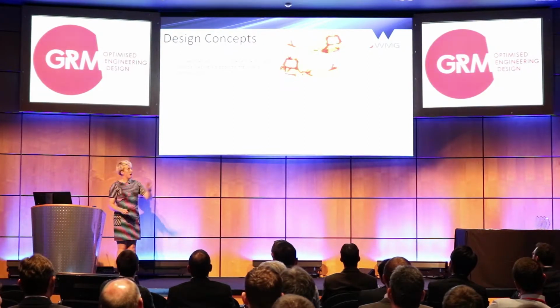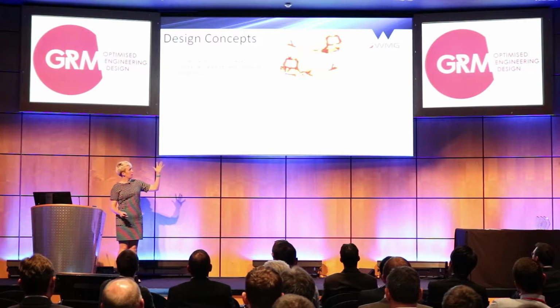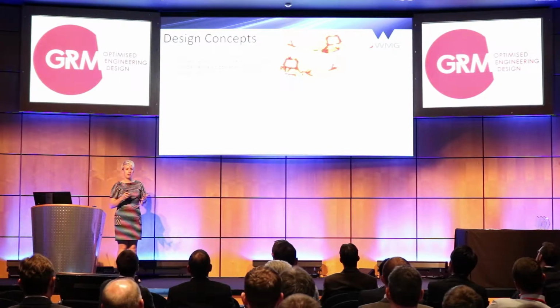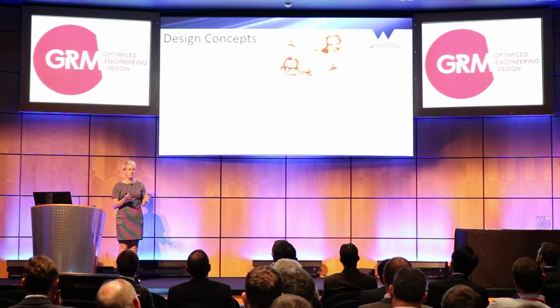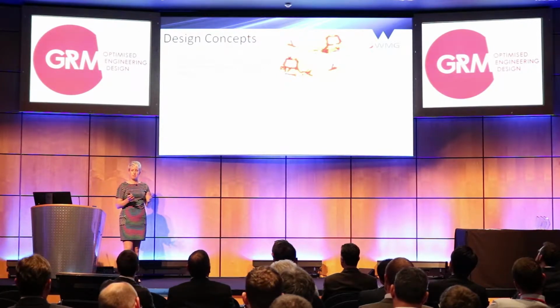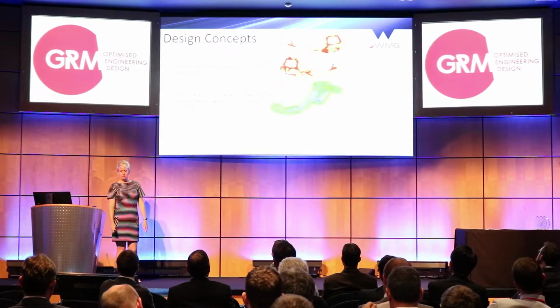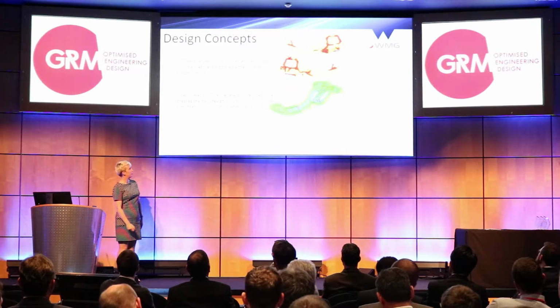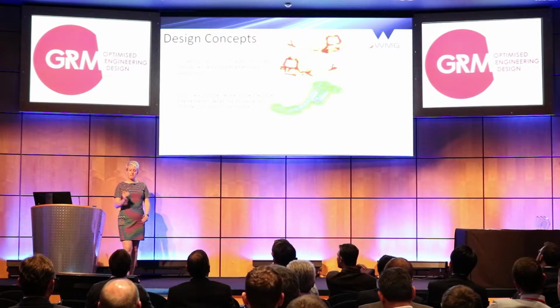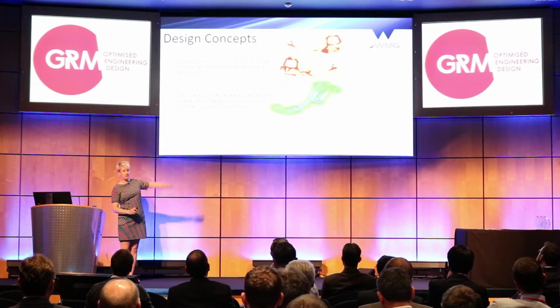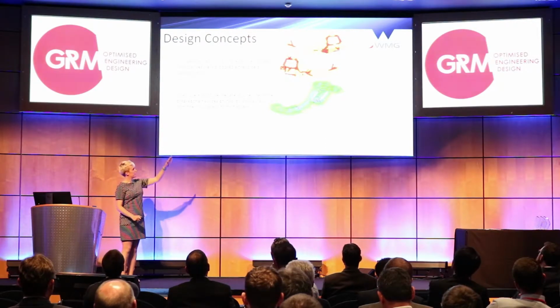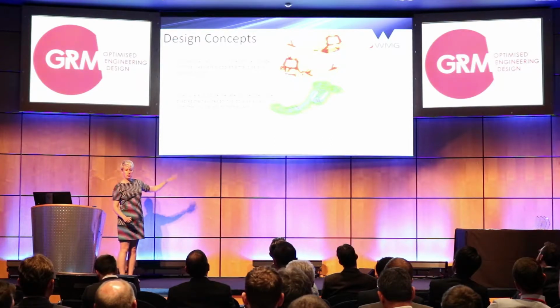However, this first design, that's like a rear and a forward of the part, had SMC on both sides. So when we add in the design for manufacture requirements, we can't achieve this. You need to be moulding against a hard surface for the pre-preg, for the green. So 2.2, this time all the clevises were put on the underside of this. And we've got this kind of ski slope transition of the pre-preg.